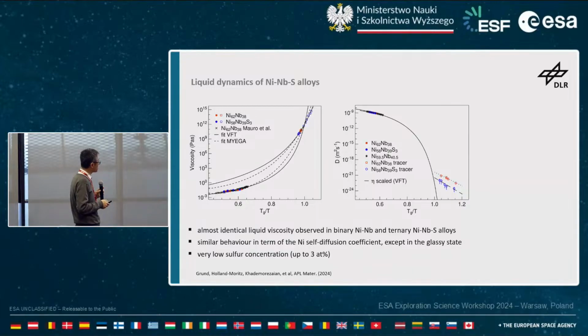This can be understood if you consider that the alloying level is very low. We are only adding 3% of sulfur, so there is not much change in the alloy composition. But I would like to remind you that the glass forming ability is increasing a lot. Just to give an idea, from 2 millimeter, which you can cast as a fully amorphous sample, to 3.5, so it's increasing by 75%.